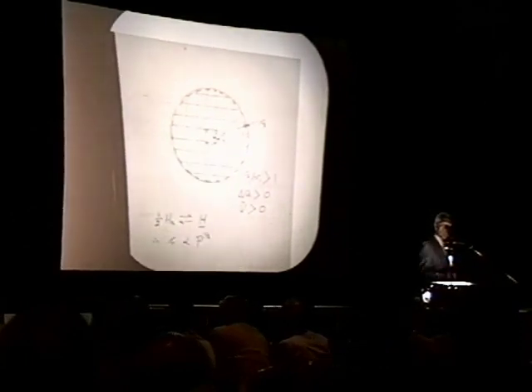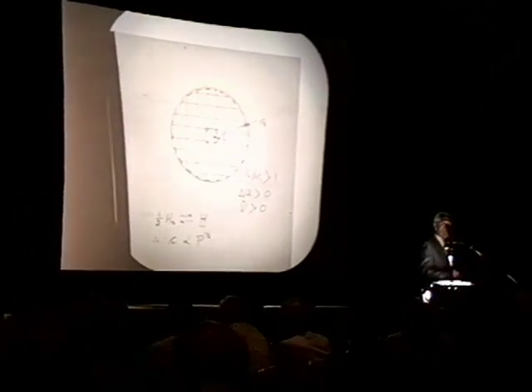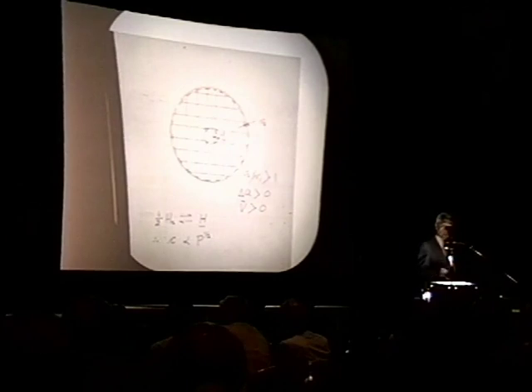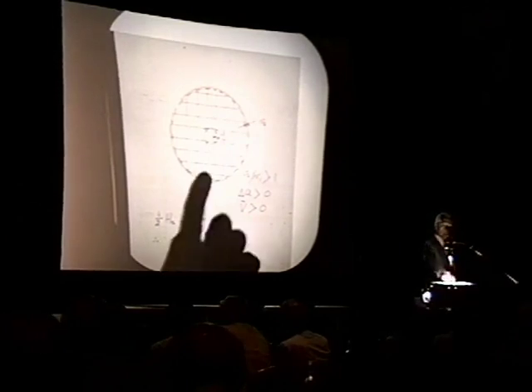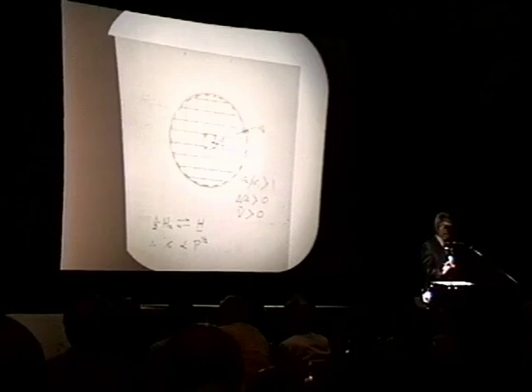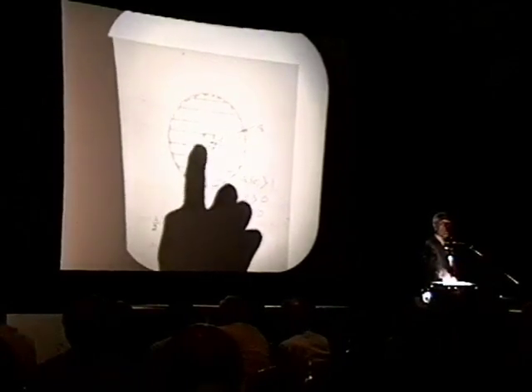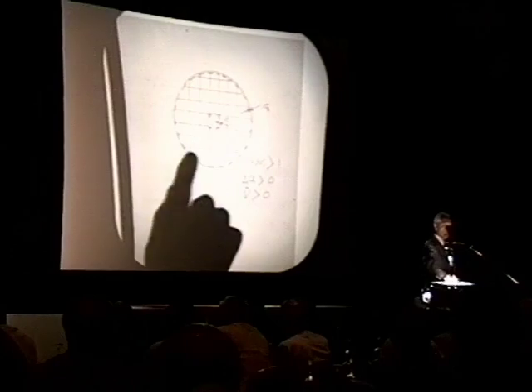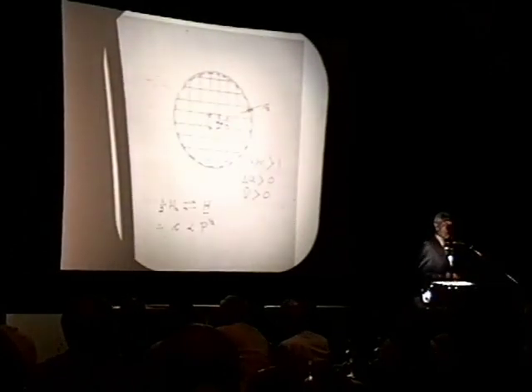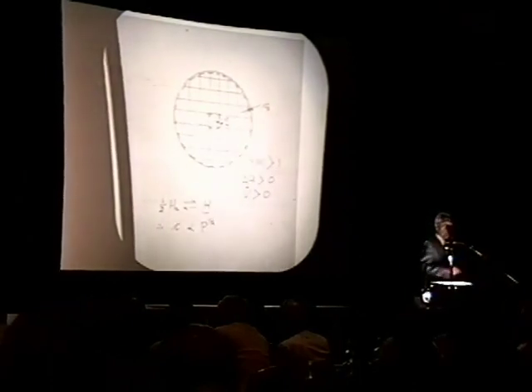When you introduce into a cavity in a solid, a cavity too small for what you wish to introduce, a larger ball, in a conceptual experiment, the cavity must expand. In the process, the wall of the cavity sweeps out a volume, which I will call V1. The external surface of the entire body sweeps out an even larger volume, V2. V2 is related to V1 by the Poisson ratio, and for a Poisson ratio of about 0.3, or about 1/3, V2 is about 1.5 times larger than V1.